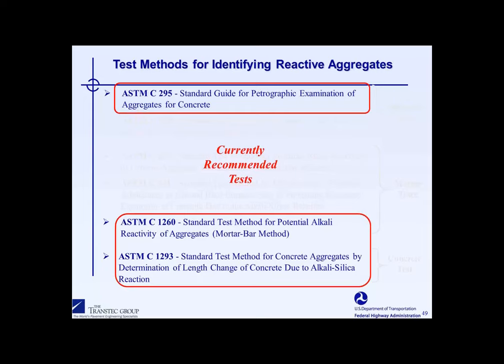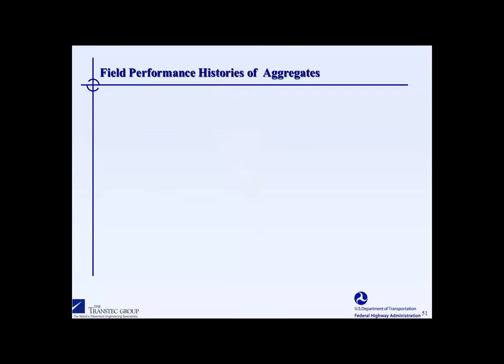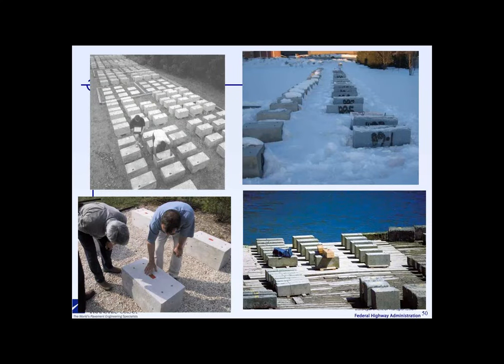So in summary, what I've discussed here today went over a variety of different test methods, but the three that we recommend the most are the use of petrography, the accelerated mortar bar test, and the concrete prism test. For all of these test methods, what I think is most important is that we underpin the results of accelerated laboratory testing with outdoor field sites. This is showing a couple of sites on top from Canada, with the cold weather on the upper right-hand corner. And the site on the bottom right is the Treat Island site.